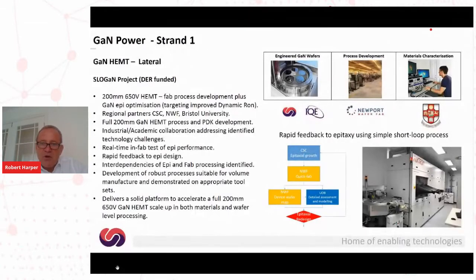So the tool down on the far right that you can see there, that's the gallium nitride epi reactor. This is a MOCVD, or metal organic chemical vapor deposition system that we use to grow the gallium nitride wafers. It's state of the art. It's capable of running five 8-inch wafers simultaneously. It's probably the tool of choice internationally for this application in terms of cost of ownership and the advanced process control it offers.